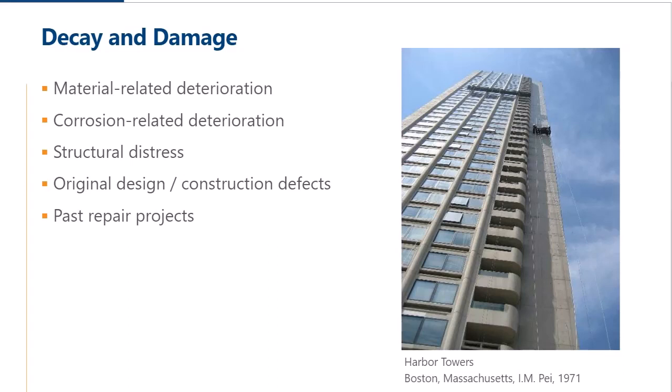The first step in the assessment of concrete is to determine the causes of decay, damage, or deterioration. This is usually characterized in several categories. The three dominant ones are material-related deterioration, corrosion-related deterioration, and structural distress. You really can't overlook problems caused during original design and construction defects, which should also be assessed. Past repair projects and their condition must also be evaluated, and there may be multiple repair campaigns to consider.